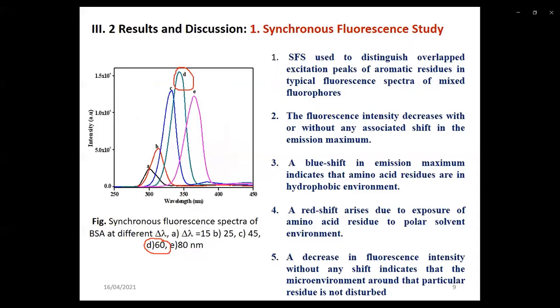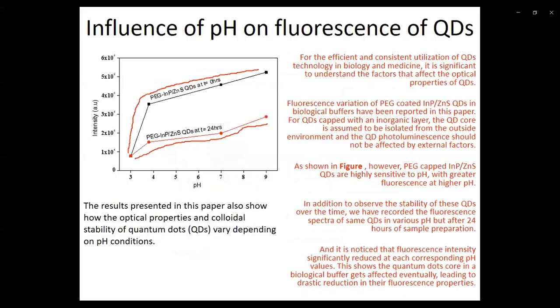Synchronous fluorescence studies have been conducted. From this study, we understand tryptophan residue is contributing more fluorescence to the HSA and BSA proteins. First, I have studied the fluorescence intensities of quantum dots at various pH values. Quantum dots have shown different fluorescence intensities at different pH values.